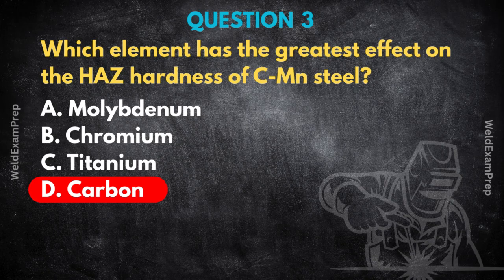If that's the case, what's a practical scenario? Say you're an inspector, you look at a WPS, and you see a higher carbon level. What should immediately pop into your head? Is it really like a big red flag for potential cold cracking? Oh, absolutely. Huge red flag. If you see a WPS for a CMN steel with a higher carbon content, or as we'll discuss soon, a higher calculated carbon equivalent value, your internal alarm bell should definitely be ringing about potential hydrogen cracking.